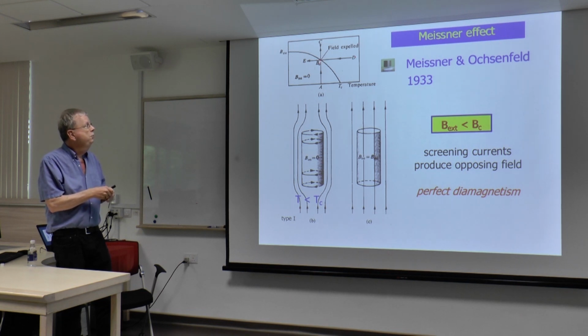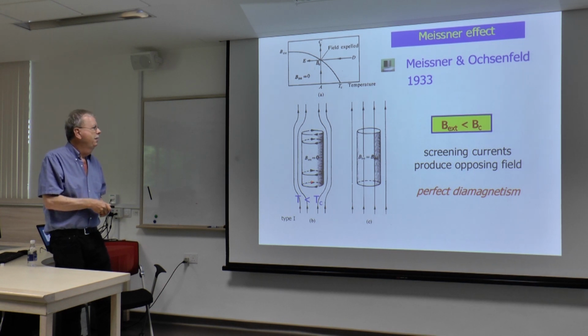If you cool through the superconducting transition temperature, which is a function of field, so it's this high in zero field, and at T equals 0 it has a critical magnetic field of this much. So if you're somewhere in between 0 and the critical field, this is the superconducting transition temperature at that field.